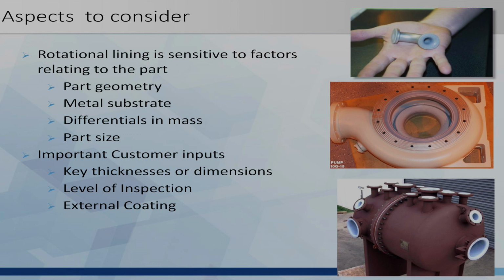The part geometry, actually, the more complicated it is, the better candidate it is. But we do need to make sure that we can get to all the areas inside to get a consistent liner. There are some products that we have to turn back just because we cannot get them rotolined adequately. For instance, if the nozzles are very small, like 1-inch diameter, sometimes if there's a jacket, then it's difficult to get the heat to the inside where we need it to get a good consistent heat transfer.